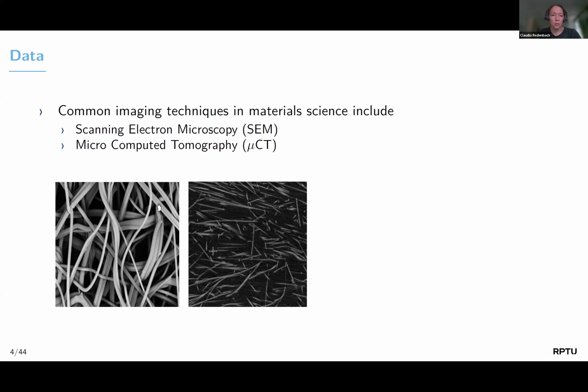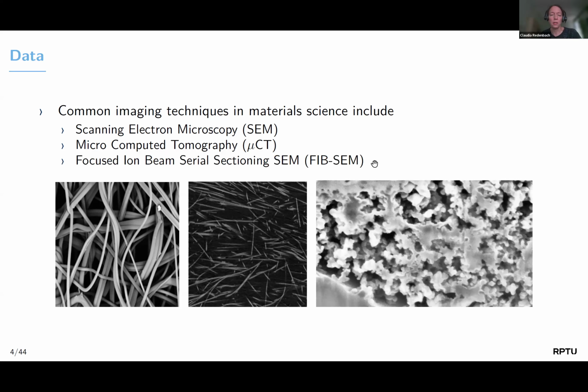The difference in voxel sizes that you could achieve is that in micro-CT, you would usually be in the range of around a micron, a little bit below. For SEM, you rather have voxel sizes in the nanometer range. If you want to get a 3D image using such a technique, you can use a serial sectioning technique, namely cutting your sample by a focused ion beam and iterating this with SEM imaging, where you could then slice-wise image your microstructure and stack that to also get a 3D image.